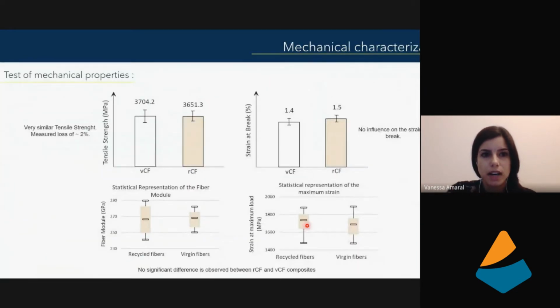Here are some mechanical characterizations. In this first part are single fiber characterizations. We have a very similar tensile strength when we compare virgin carbon fibers with recycled carbon fibers. We have a loss that is less than 2%. We have seen no influence on the strain at break when we compare both fibers.